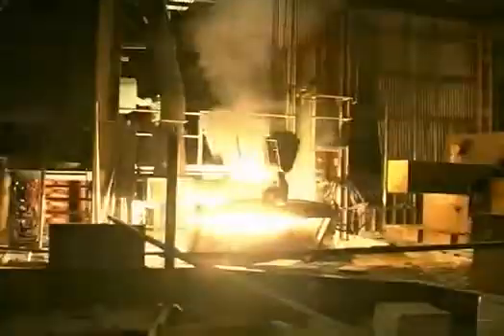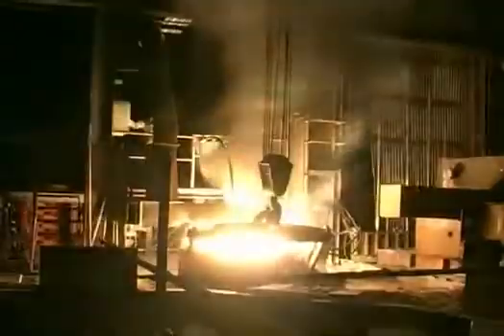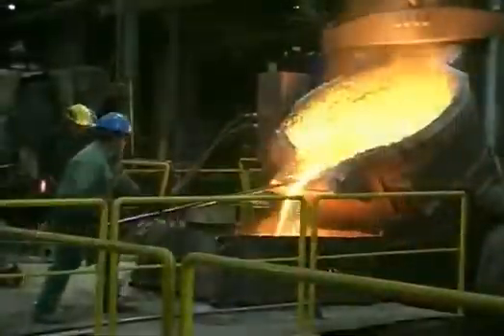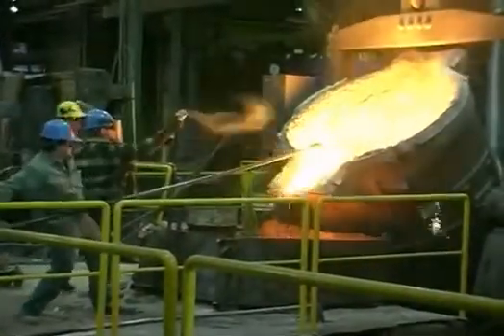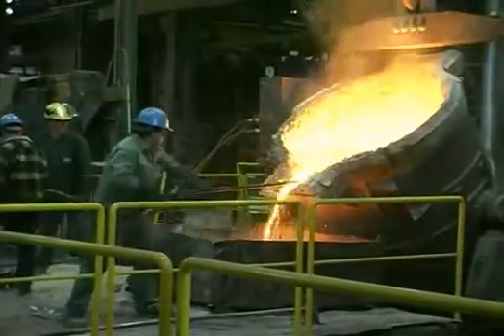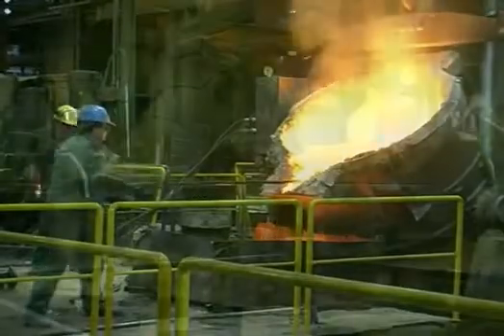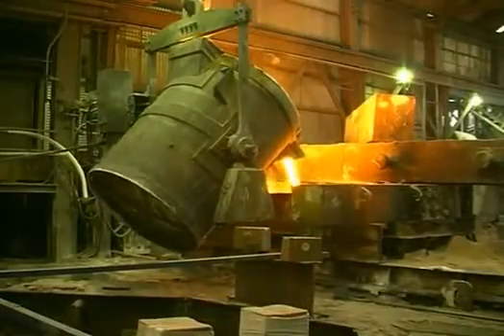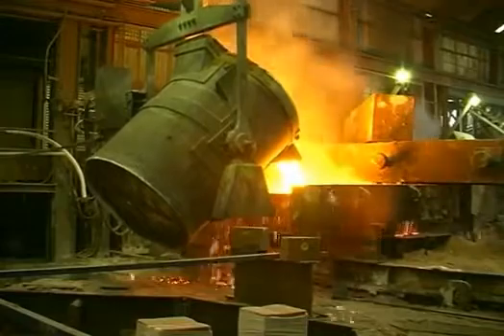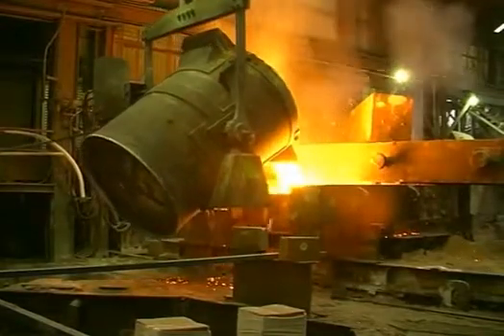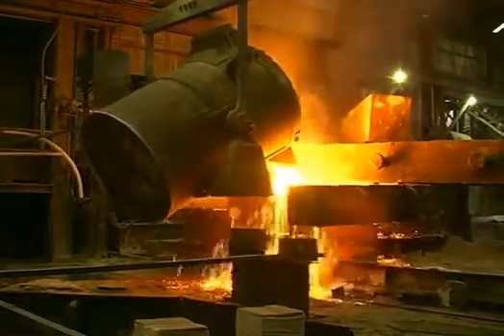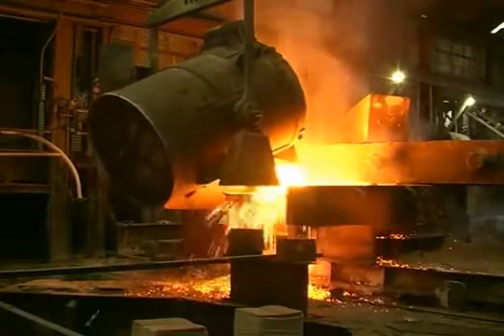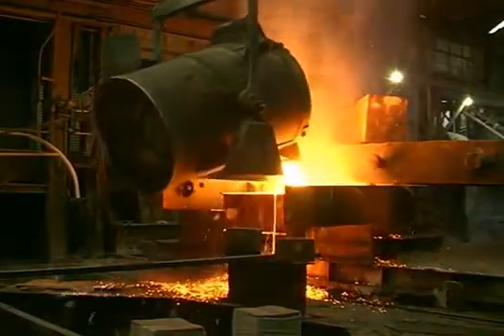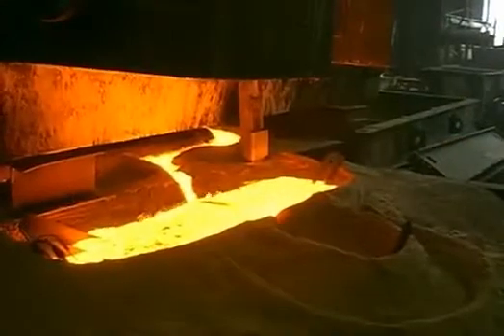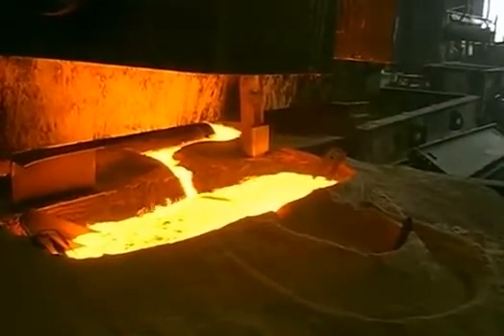These will cause the carbon in the melt to form little spheres, thus producing a ductile iron, a material that is much stronger and tougher than grey cast iron. 75% of all castings produced in this foundry are ductile irons. 48 tonne of metal will be poured to produce a 40-tonne casting. The additional 8 tonne will form heads and risers. This metal is not wasted, but will be cut up and recycled.